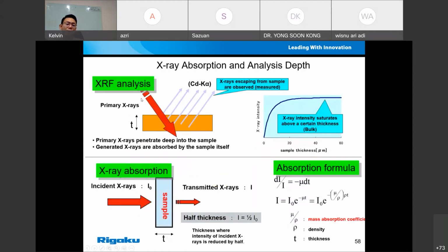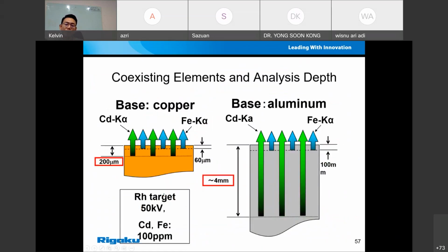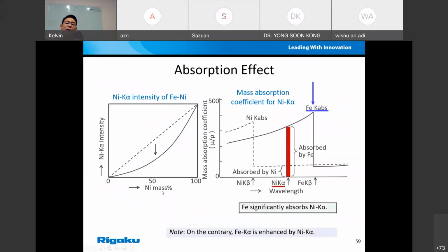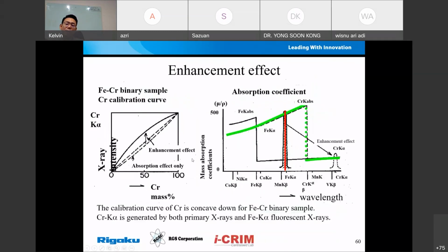And there is also an absorption effect, and also enhancement. Generally speaking, where the Z value is 2 positions higher than your element, it is going to enhance. For example, here the Fe significantly absorbs the nickel, and then the Fe intensity is going to be enhanced by the nickel wavelength. The other way around, where you have chromium with Fe, it is the reverse. So it becomes a different type of effect.